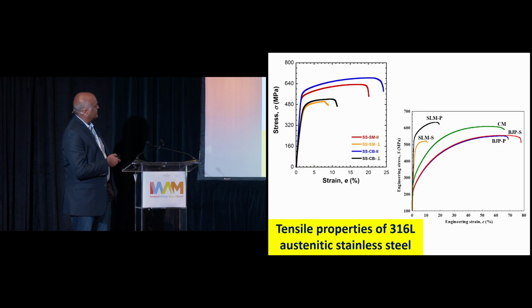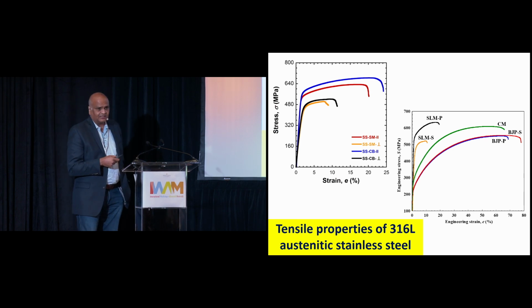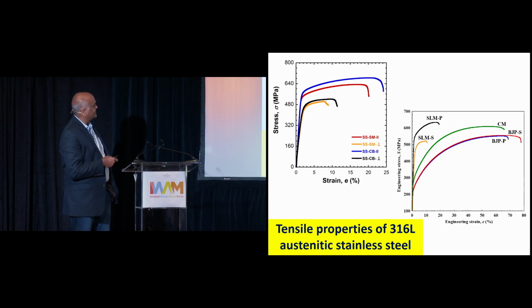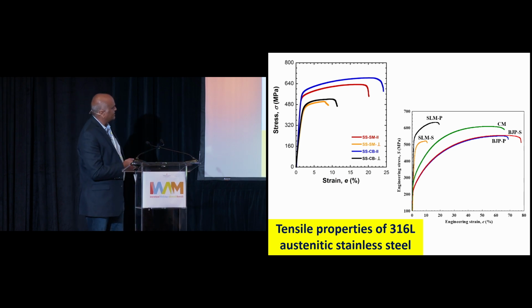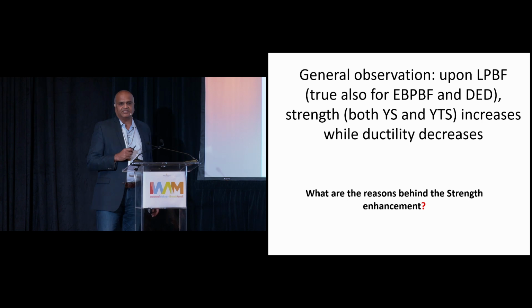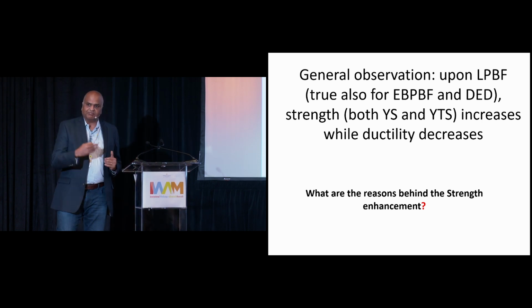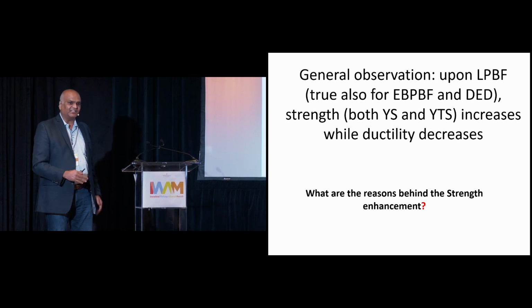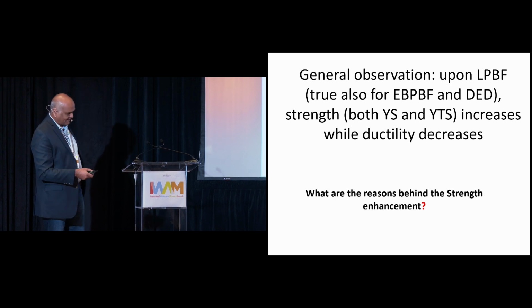That's the thing—this is also true for 316L, an austenitic stainless steel. The conventionally manufactured alloy is fairly ductile, but if you do laser powder bed fusion, the strength increases while ductility decreases. This is a general observation for most 3D printed alloys compared to their conventionally manufactured counterparts: strength goes up, ductility decreases.